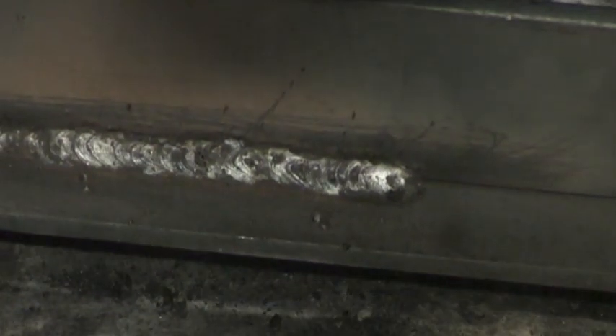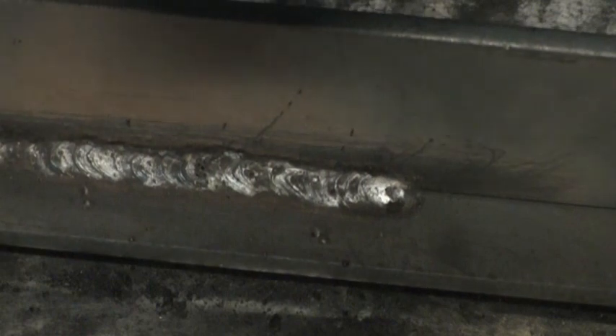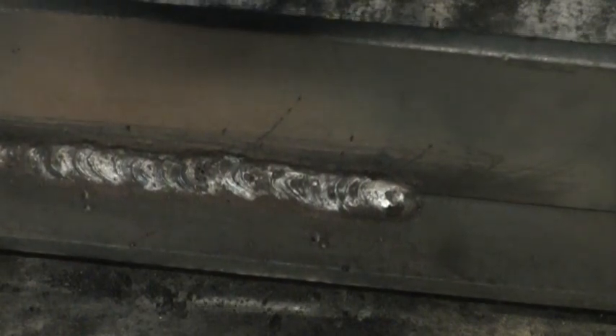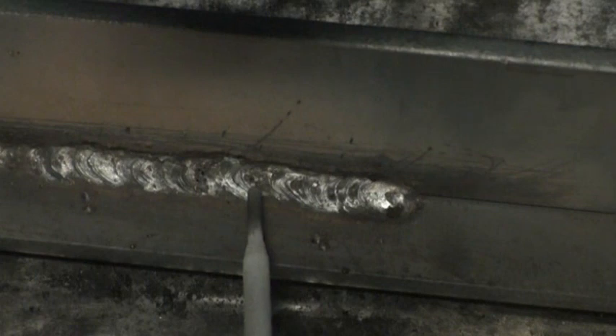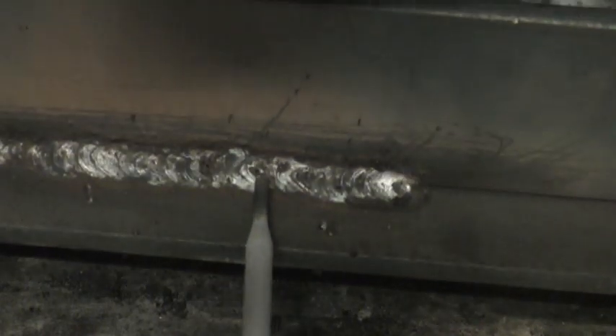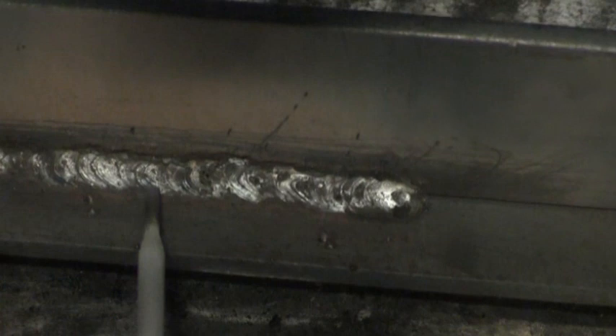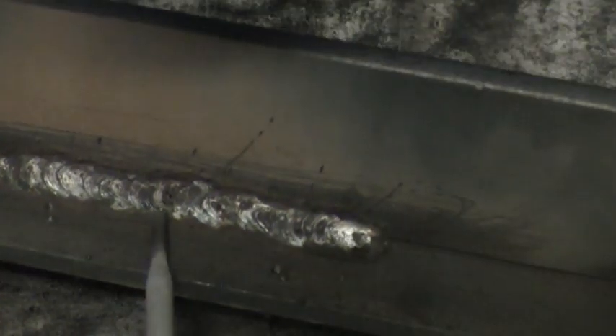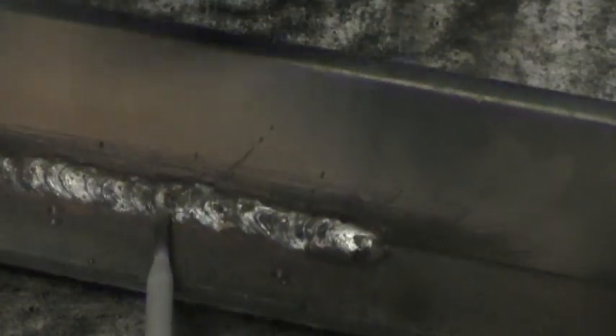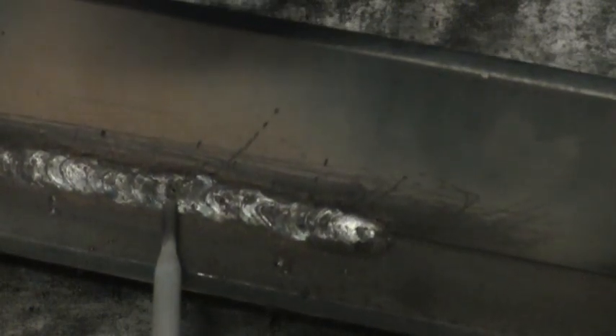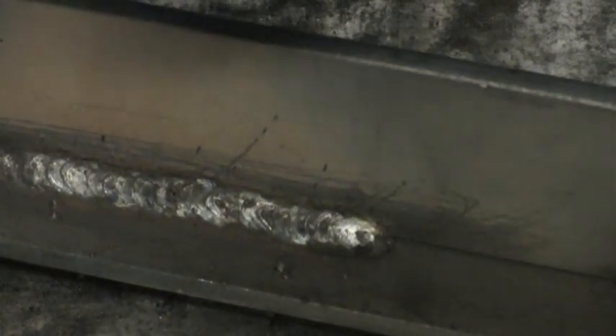So as I've held my arc too long, one of the effects is that my bead is flat. Okay, the bead is very, very flat, and I've actually got holes in the weld. You can see, if you look carefully, I'll try to point these out. Right in through here, that's actually a hole in the weld. That's not a dimple from the slag hammer. And I have some small holes right in here that are hard to see, get the light just right. Okay, so those holes are porosity.